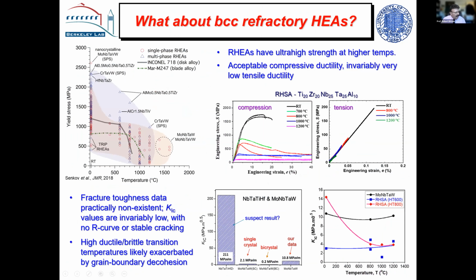So just last few minutes, there is a second type of high entropy alloys called the BCC materials. These are the refractory ones, and these are renowned for having very, very high strengths. This is yield strength versus temperature. These materials like molybdenum, niobium, tantalum, tungsten, and molybdenum, tungsten, vanadium, tungsten have much, much higher temperature strength than nickel-based superalloys. So they're potentially very exciting materials.